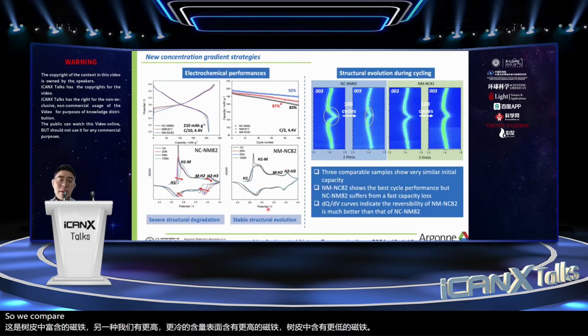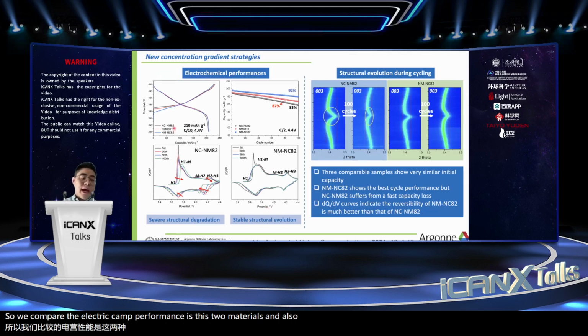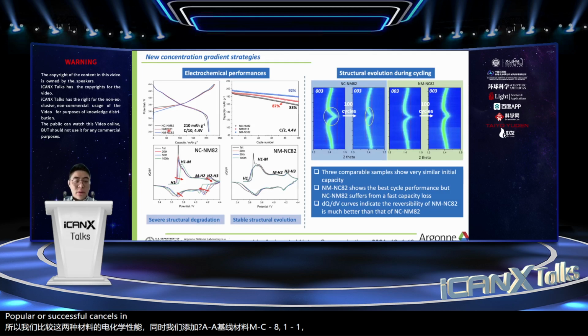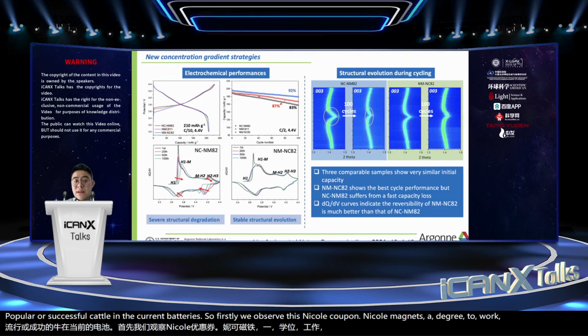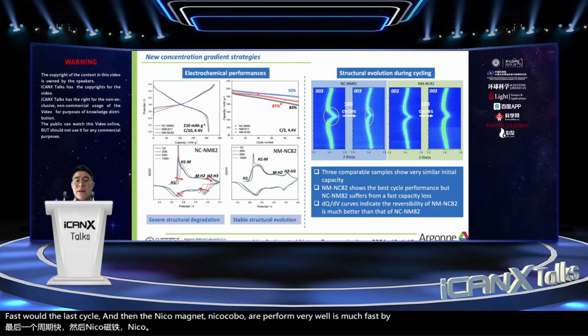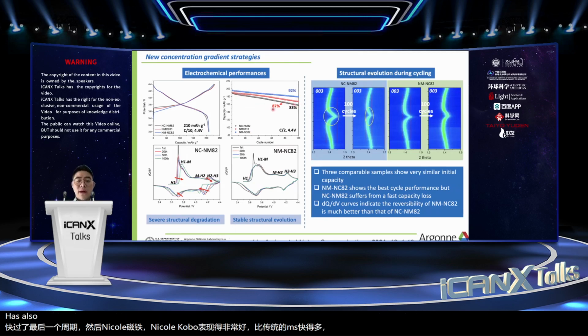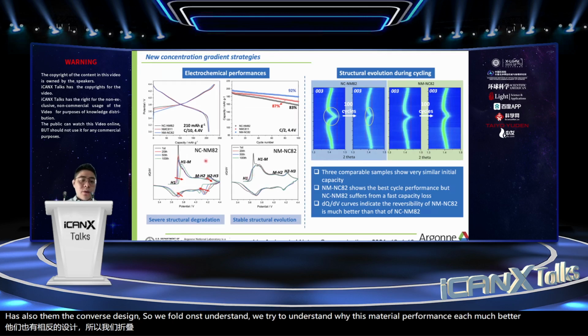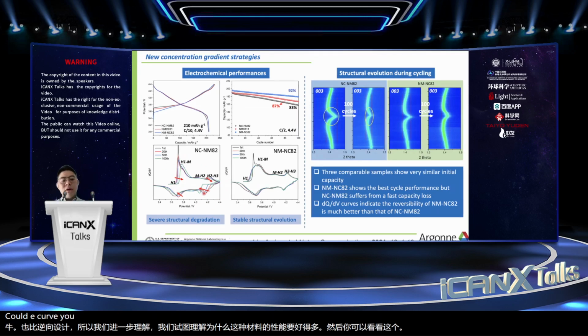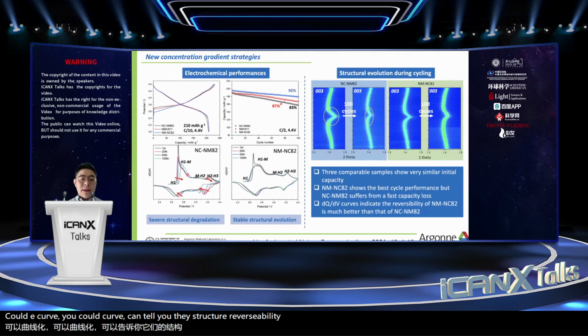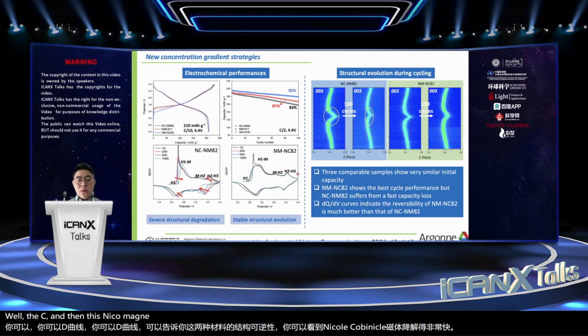So we compared the electrochemical performance of these two materials, and we also added a baseline material, NMC 811, that is a very popular and successful cathode in current batteries. Firstly, we observe that the nickel cobalt–nickel manganese design degrades very fast over the long cycle, and the nickel manganese–nickel cobalt design performs very well. It's much better than the conventional NMC cathode, and also than the converse design. We try to understand why this material performs much better, and you can look at this dQ/dV curve. The dQ/dV curve can tell you the structure reversibility of these two materials. You can see the nickel cobalt–nickel manganese degrades very fast over the cycle, and this nickel manganese–nickel cobalt is still very stable over the long cycle, right?